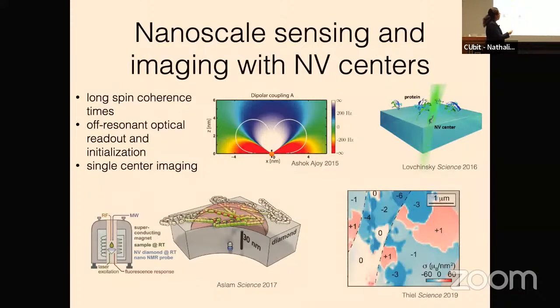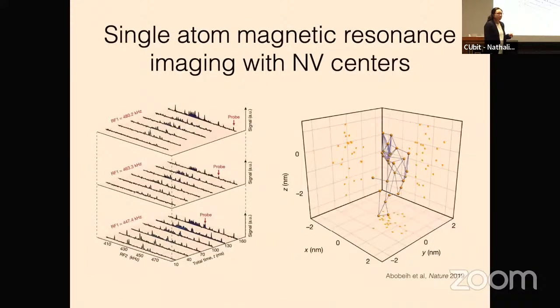And that really gives you this really amazing spatial resolution. So there have been a number of efforts trying to push the frontier of looking at, for example, single molecules external to the diamond. There's this beautiful work where people take small volumes of liquid and do nanoscale NMR, much like a multi-well plate type experiment in a microbiology lab. And then there's also a robust community trying to use NV centers to do condensed matter sensing. This is an example from Patrick Maletinsky's lab in Basel, where they have a scanning tip with an NV center in it, and they can look at the magnetic domains in, for example, a 2D magnet. This is chromium triiodide, and they were able to learn things about the nature of magnetism in this sample.